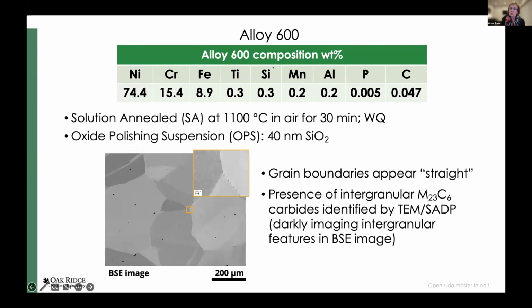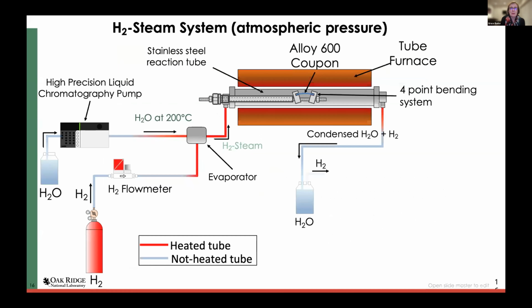Okay, so the alloy of interest is a very simple, straightforward one. It's termed alloy 600, nickel with about 15 weight% chromium, about 9 weight% iron, but you'll see low amounts of some other elements here. And I would call your attention to the titanium and the aluminum here. Solution annealed, 1100 C, water quenched, polished, and another backscattered electron image where you can see a nice recrystallized microstructure, but also some very fine darkly imaging features at the grain boundaries that, doing TEM and electron diffraction, have been characterized as M23C6 carbides.